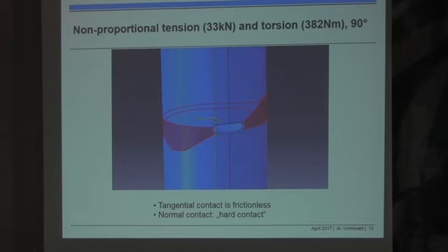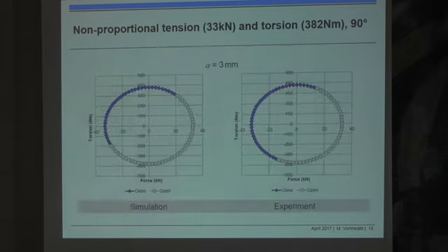We applied a cyclic plasticity model of the Chaboche type in order to get ratcheting in an acceptable way. And we set up a node release scheme, so we started without crack, and here at that facet we opened the debonding of nodes further and further with large steps, and Professor Antunes would not be very familiar with our node release scheme because it was much too rough. However, we had to arrive at some result, and one of these results could be expressed in this way.